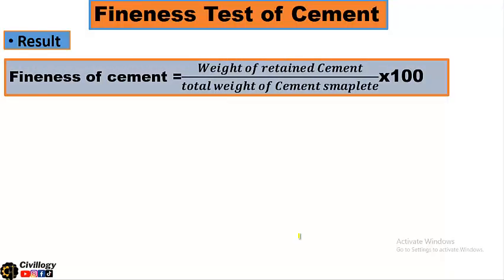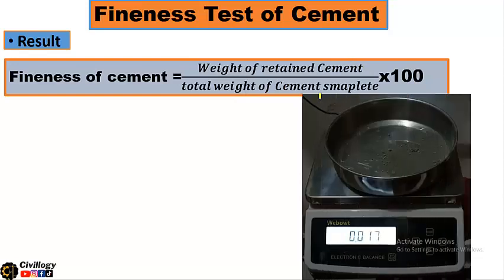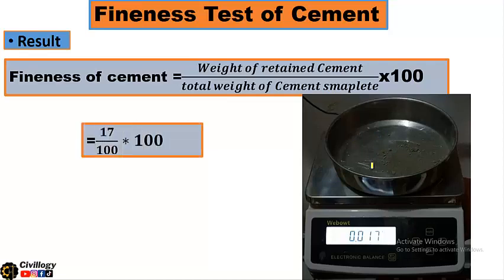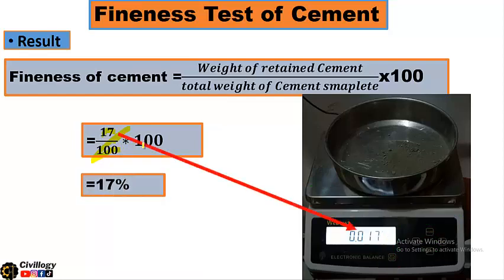In our case, to find the fineness of cement, the formula used will be, as you can see over here, weight of retained cement divided by total weight of cement sample. When we weigh the retained material, it comes out to be 0.017, which means 17 grams. So by putting in the values, the weight of retained cement is 17 grams divided by the initial weight of the sample, W1, which was 100 grams, and multiplying by 100 to get it as a percentage, it comes out to be 17%.